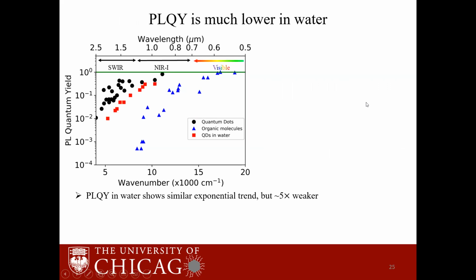And here I have plotted the quantum yields of quantum dots solubilized in water at different wavelengths. We can see that we have a similar trend as the quantum dots in nonpolar solvents, but the quantum yields are around 5 times lower. I want to emphasize that these are quantum yields for several different materials, including lead sulfide and indium arsenide. So this tells us that there is some universal trend which is resulting in this low quantum yield as we go to longer wavelengths.